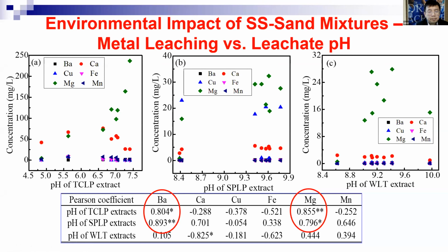We found that barium and magnesium are highly correlated with the TCLP and SPLP leaching pH, so they really relate to each other. But the other ions among them didn't show any correlations to each other. So this gives you data showing how they relate to the leaching pH.